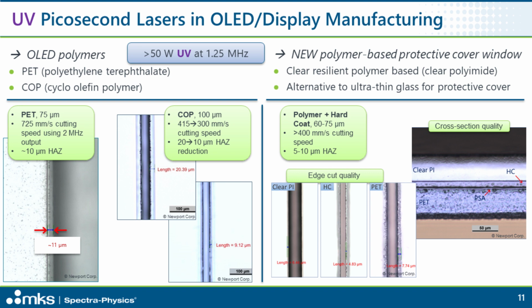The bulk of these results will be with an infrared picosecond laser, but first I want to touch on some OLED processing we've done with the UV picosecond laser. In this case, our current flagship 50-watt UV laser at 1.25 megahertz, the IceFire 355-50. So on the left, we have a couple polymers, PET, polyethylene terephthalate, and COP, cycloolefin polymer. PET is really a workhorse for OLED displays. It's used in many areas, including the substrate, but also for the touch panel and other areas. And we see a nice, clean cutting result with less than 10 micron heat affected zone.